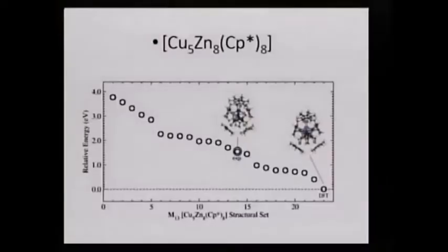Okay. So until here, everything is all right. Our calculations are matching with the results of the experimental guys. So now starts a different kind of conversation. Here we perform the same kind of exchange of positions on the atoms, and we can find that the experimental structure pointed out here is different from the lowest energy configuration achieved by DFT.